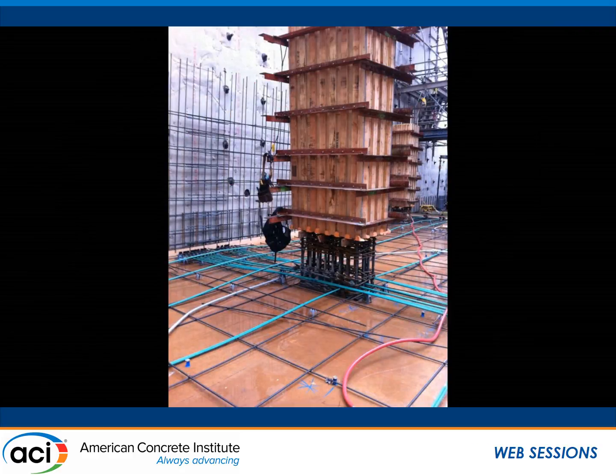The slab mixes, we had a requirement for shrinkage, and they had a test for shrinkage not to be more than 0.04. And this is what I was mentioning earlier, that the minute they pour the slabs, the formwork of the columns are in place. They drop that formwork on some dobies here around it, and then they just pour the column almost the same day.